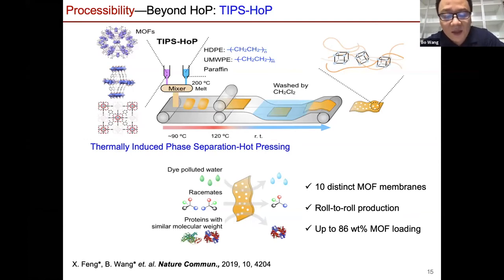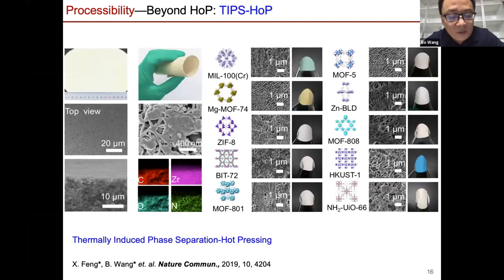In this case, we made 10 distinct MOF membranes through this roll-to-roll process, and it has up to 86% of MOF loadings. At the same time, the membrane by itself is very strong, and it can actually withstand high pressure. We use this membrane for gas separation and the liquid phase separation.